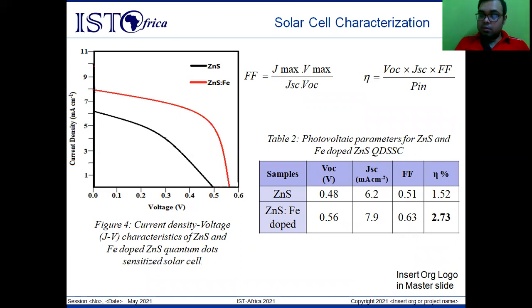So in table 2, we can actually see that in case of normal, undoped zinc sulfide, the efficiency is around 1.52%, for iron doped, transition metal iron doped zinc sulfide, the efficiency has increased to 2.73%. In terms of low cost photovoltaics, this is a significant increase.